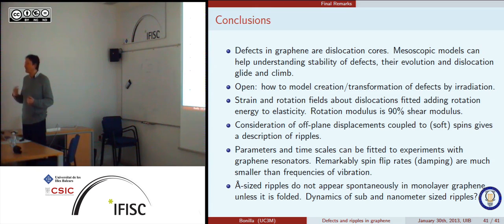So even if you have a rotation, since it produces no energy, linear elasticity doesn't care about that. Now, it turns out that the minute you have a dislocation, even in classical elasticity, you are inducing a rotation, and you can calculate it. Not only that, the rotation is infinite at the center of the dislocation.